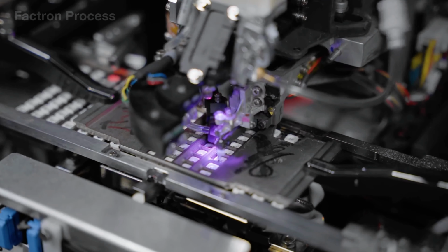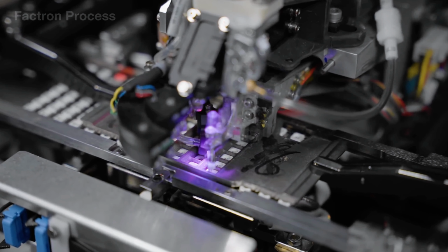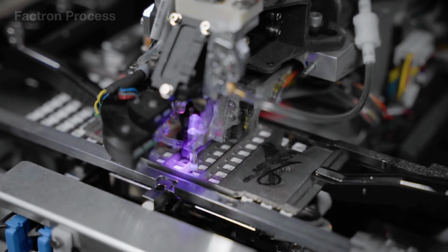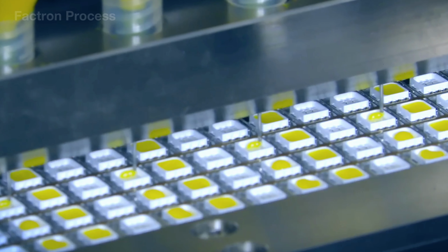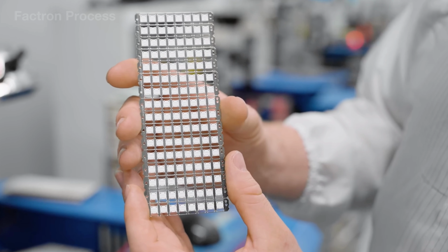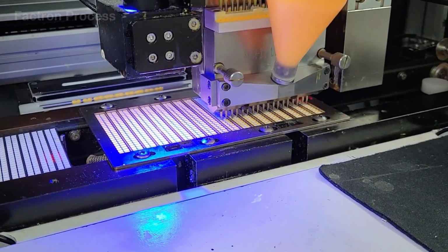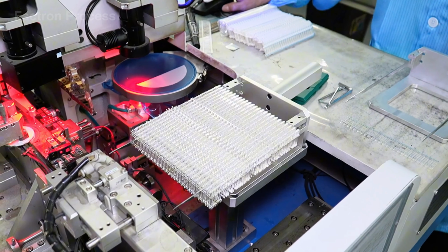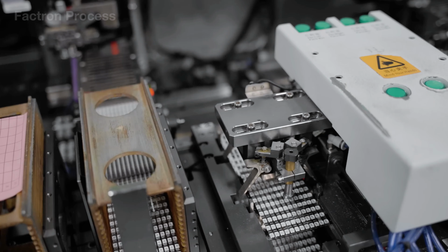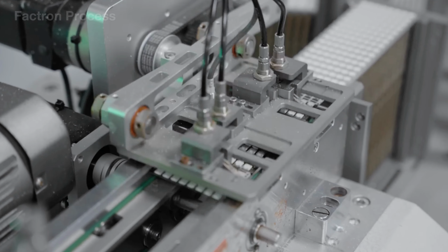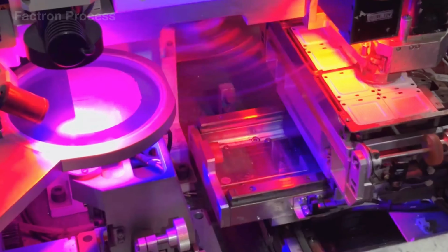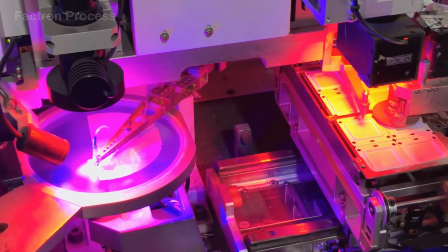Before the chip is mounted, the machine deposits an extremely small amount of silver adhesive or bonding material at the center of the package. This layer secures the chip while also conducting electricity and transferring heat downward. Too little adhesive may cause the chip to detach, while too much can overflow onto the electrodes. Immediately afterward, the die bonder begins operating.